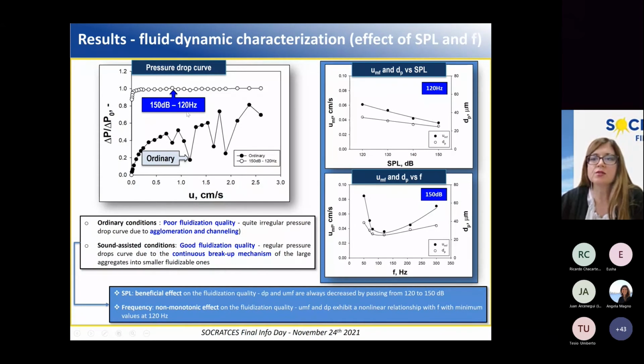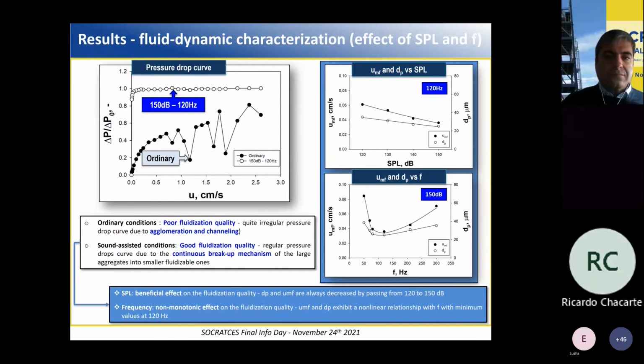The role played by sound intensity and frequency has also been assessed. In particular, you can see here the experimental values of minimum fluidization velocity and fluidizing particle size as functions of sound intensity and frequency respectively. In particular, the sound intensity has a beneficial effect on the fluidization quality. This evidence is due to the fact that with increasing intensities, more and more energy is introduced inside the bed, thus making the breakup mechanism more and more efficient. For frequency, an optimum range can be found. In particular, when the frequency is too high, the sound is not able to propagate inside the bed, and is not so effective.